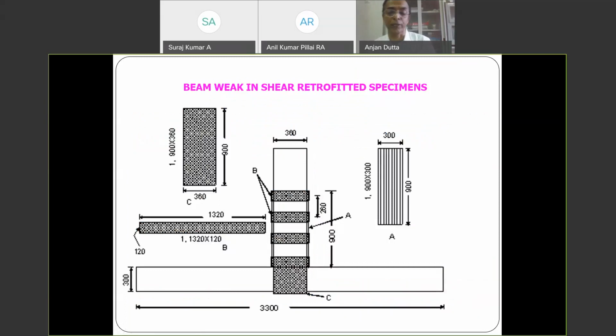The next specimen is your beam weak in shear, and you can see that now the shear reinforcements are increased. You have more strips to get rid of the weakness in shear, because shear mode of failure is highly unwelcome, because it's a very brittle mode of failure. Always, if at all a structure fails, it should be in the flexural mode. So we have introduced the shear reinforcement in the form of stirrups, again using FRP, and simultaneously have looked at the joint region also.